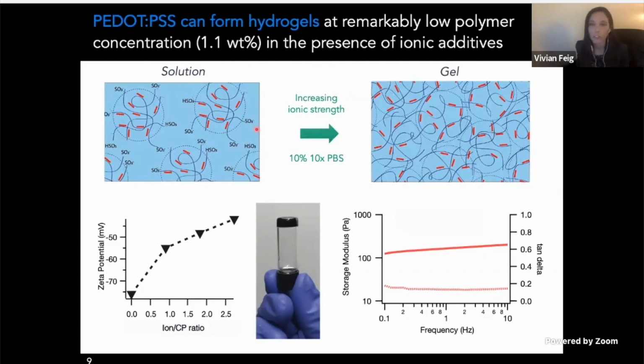So here, for instance, we've mixed PEDOT:PSS solution with 10% of a 10x concentrated phosphate buffered saline solution so that the final concentration is about the same as regular PBS. And we see that as we mix, the zeta potential increases, showing that we're screening those repulsive effects. And the resulting material is this solid-like opaque hydrogel, where we can get a little bit more insight into the mechanical properties by doing oscillatory rheometry.